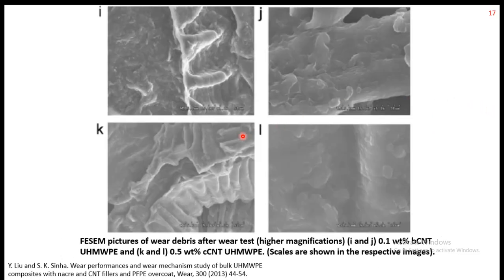This shows the SEM picture of the same polymer composites I showed you before, and you can see that UHMWPE, even after adding some filler, acts in a very ductile manner. We don't see any crack. All we see is deformation of the material in a very ductile manner.